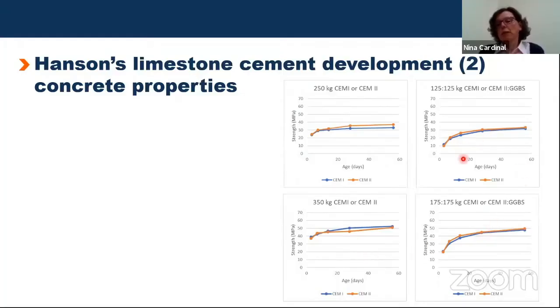They have also made what are basically the future CEM IIs. They have blended the cement with 50% GGBS. And again, as you can see, there is virtually no difference between the two. And in fact, the CEM II at the early ages here has a slightly better strength performance than the CEM I. This is a well-known effect of additional nucleation sites we get from the fine limestone in the cement.